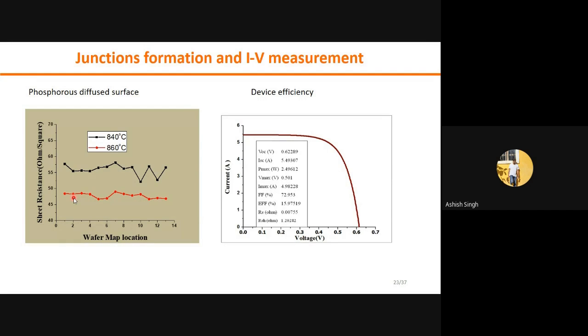So at 860 degrees Celsius, we got uniform sheet resistance throughout the wafer, and then we removed the silicate glass, and on the backside we put aluminum and did the firing to make the back contact as well as the BSF, back surface field, of the silicon solar cell. On the top we deposited silicon nitride as an anti-reflection coating and passivation layer. After that we measured the cell efficiency.